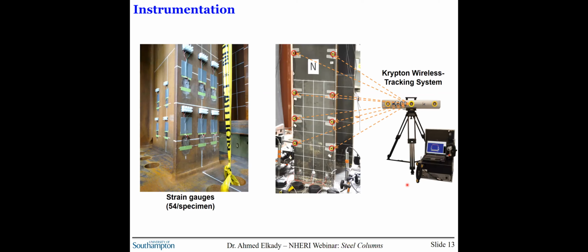A brief word here about the instrumentation. In addition to the standard force-displacement acquisition that we typically do in such tests, it's worth noting that we installed a large array of strain gauges, about 54 gauges per specimen. This is to capture the neutral axis shifting in the cross section, to track the extent of plastic strains at the column end, and also to track the location of the flexure inflection point throughout the test. We also used a wireless tracking system to measure the out-of-plane deformations and the twisting of the column along the height.